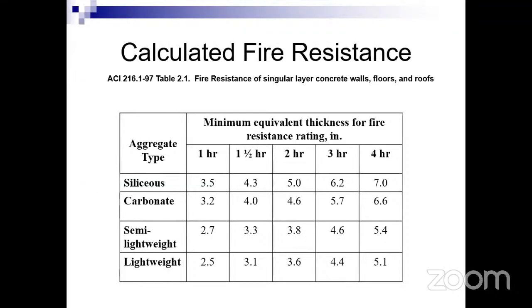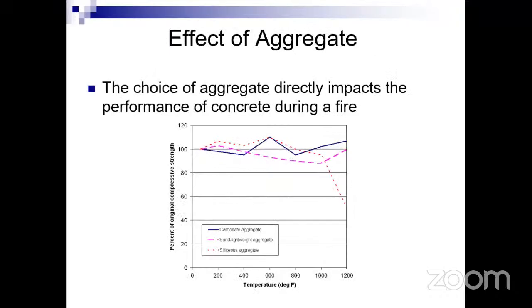We can see here that for a 1 hour, 1.5, 2 hour, 3 hour, or 4 hour fire, for various aggregates, the thickness of the particular element is given here. So we can see that lightweight or semi-lightweight concrete elements have better fire resistance in terms of thickness and give less structural cost than siliceous or carbonate aggregates. We can see in this table as well that the choice of aggregate directly impacts the performance of concrete during a fire.